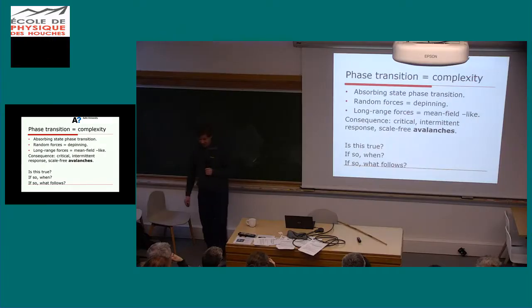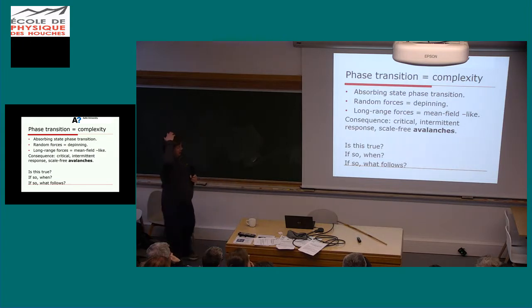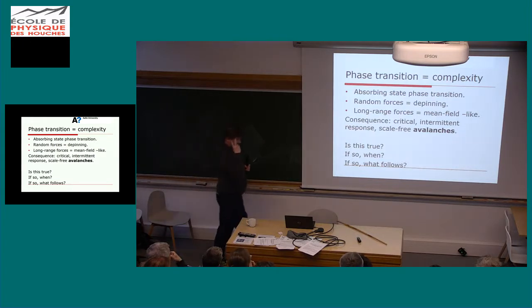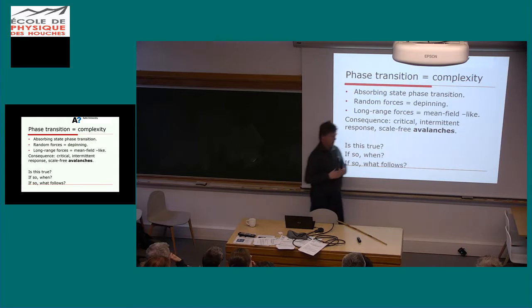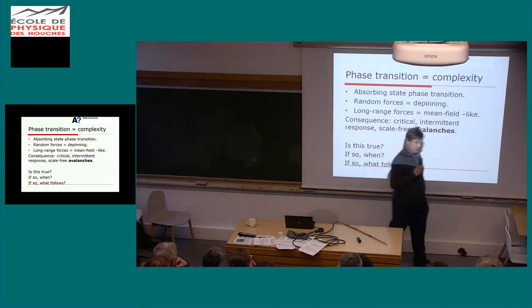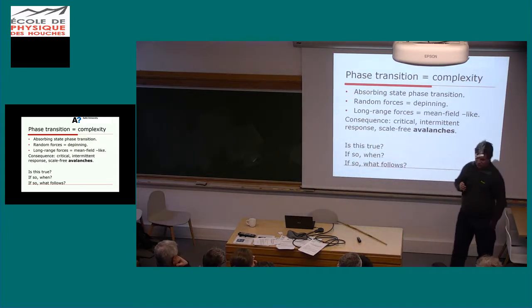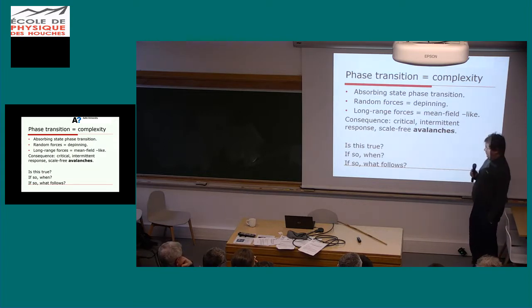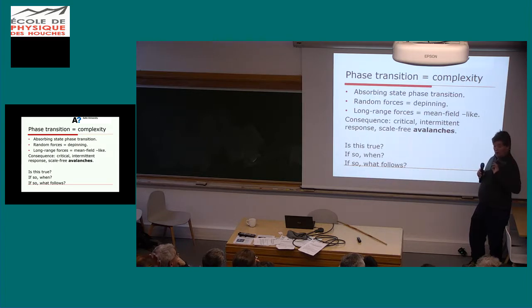And this is what I say here. The only complexity if you start arguing like this is that there are two things that are important. One of which is that these very long range elastic interactions of dislocations cause this kernel to be also anisotropic and not positive definite, but that's another story. And then the idea is that you sort of expect that this landscape is, as in a good depinning, quenched, but of course it slowly changes as the dislocations move, so well. Anyway,